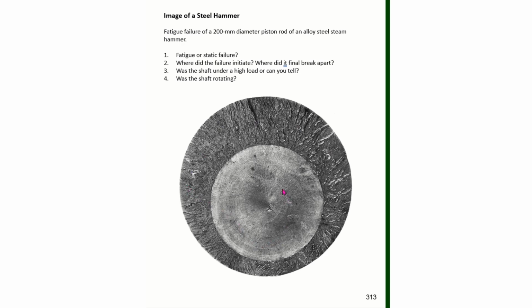But a fatigue surface, it propagates a crack in one usage or one rotation, and then that crack is pushed together again, then opens up a little bit, and as the cycle continues, it works itself back and forth on top of itself. And so the failure surface is usually much more smooth than a brittle fracture failure surface. And that's because as the cracks propagate, they push back and forth on each other, smoothing out the rough edges.